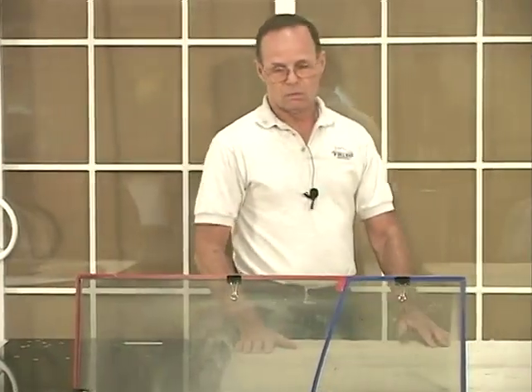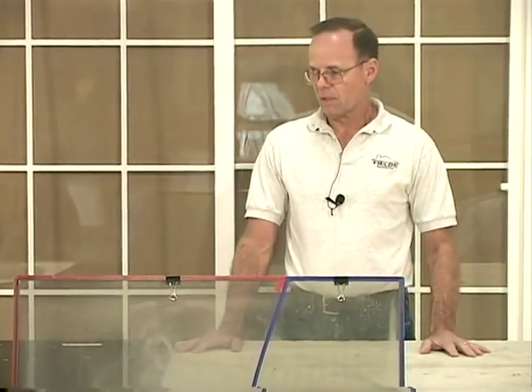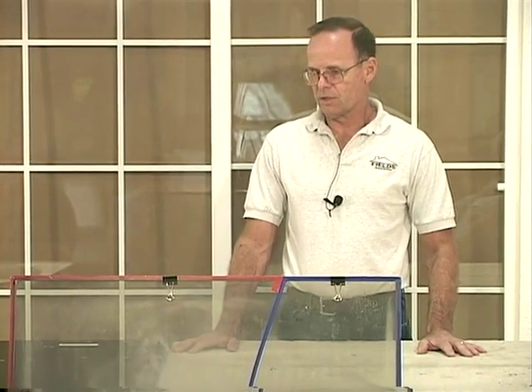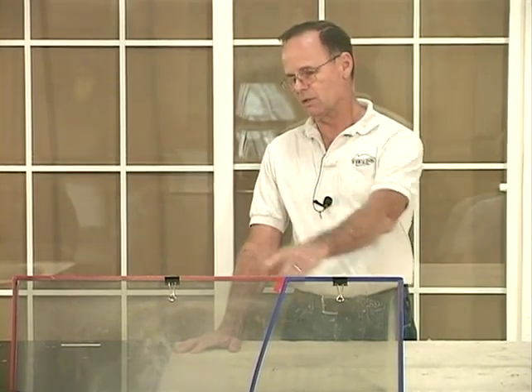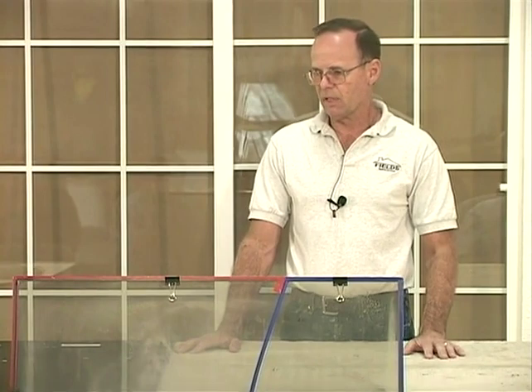There's also one thing you got to be careful of. I have never seen a corrosion like you see on this window here. I have never seen that on the tin side of glass. Usually when you have corrosion on glass, you will only have it on the air side. You'll never have it on the tin side. For some reason, the tin protects the glass from corroding.